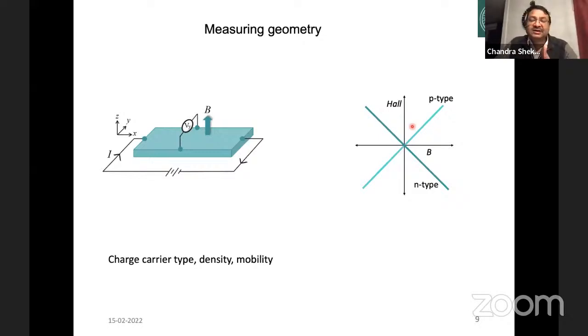So this behavior is for a non-magnetic material. When we measure a Hall voltage or Hall resistivity or Hall resistance with the variation of the field, we have a linear voltage, depending upon the nature of the charge carrier. Suppose this charge carrier is p-type or hole type, this voltage varies with a positive slope. If we have a negative charge carrier like an electron, this slope is negative. So by measuring the Hall voltage, we can say what type of charge carrier is inside the material.